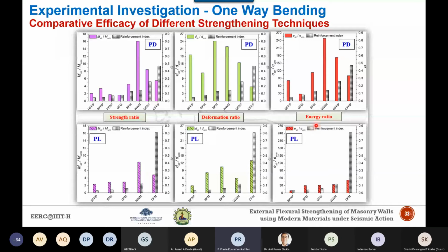Okay, so here you can see that, especially in case of the FRP composites, there is a strength enhancement, but it is comparatively smaller. Why? Because in case of the FRP, the predominant failure mode is the debonding. And as I said, here you can see that the carbon fiber is showing the highest strength, whereas the hemp fiber is showing the lesser strength, because the tensile strength capacity of these two composites is comparatively very small for the hemp and basalt compared to that of the glass fiber and the carbon fiber. There is another important point which I need to address here: if you are using a low tensile strength composite like hemp, basalt, and flax, they are able to utilize the reinforcement to its full capacity.